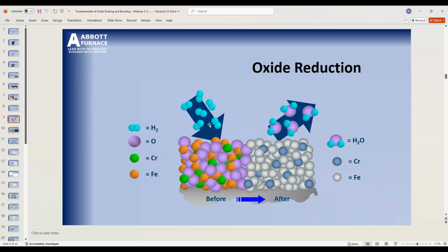So in this case, we're showing here we have chromium and iron and oxygen and hydrogen coming down, and it would be like a stainless steel part, or even an iron part is the same, right? We have to remove the oxides, and the hydrogen grabs that oxygen. It forms water, H2O, and then the water, because we're above the boiling point, turns to a vapor and it floats away, and we push it out the front of our furnace and get rid of it. And so we can clean those surfaces by reducing the oxides.